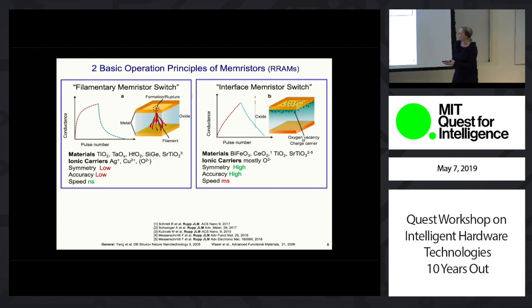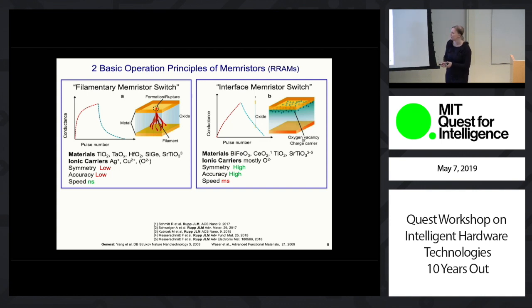If that happens, you will have a very abrupt change in resistance or conductivity, and you will see a very quick onset of the conductance to the other state that you set. However, later this becomes retarded when swinging back to the state once you take the signal off. The consequence of that operation on an atomistic scale is that you have a very low symmetry for these filament-based memristors, and the second part is that your accuracy is very low. But the good news is that because you have a very fast motion of cations, you have a very fast switch speed, which can be in the nanoseconds.